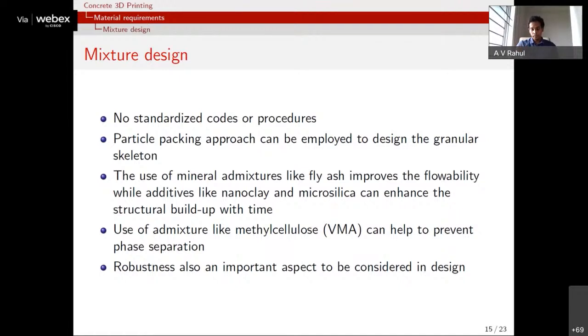Also, sometimes during pumping, you can encounter issues like phase separation, which you can avoid by using admixtures like methyl cellulose. And robustness is another key aspect you need to consider in mix design. One problem with 3D printable concrete is that the range over which it actually works is very narrow, especially if you have a batch change in one of the materials. For example, you're using a particular type of fly ash, and the batch of fly ash that you're using has changed now, then you might see some change in the workability of the concrete because of this batch change.